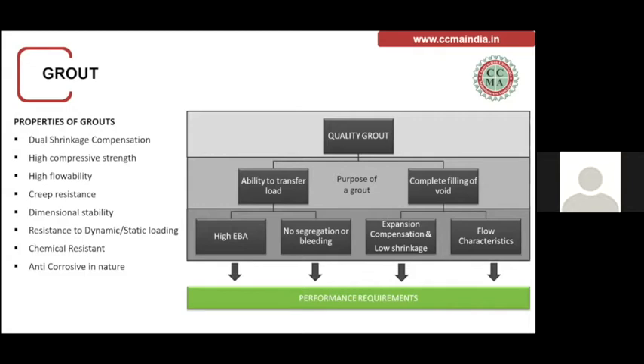And when we talk about load transfer, the effective bearing area should be high, because only if the contact surface area is high will it be able to transfer the load properly, and there should not be any kind of segregation or bleeding in the grout. When we talk about filling the voids, once the void is filled, the grout has to give shrinkage compensation, like expansion and compensation, which is one of the important parts of the grout, so that at a later stage, if there is any shrinkage, there would be no void inside these connections.